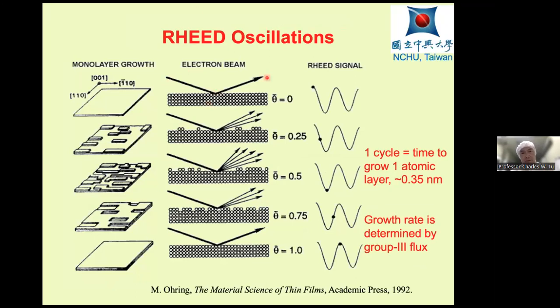And so in the electron diffraction, the specular beam is at its highest because the surface is smooth. Then as we deposit more, at the first quarter of a monolayer, 0.25 here, these monolayer high islands form randomly on the surface, and so the surface is rough. The electron intensity decreases and there is more diffuse scattering. The surface is roughest when we have a half monolayer, so there is a lot of diffuse scattering and the specular reflection is at the bottom.